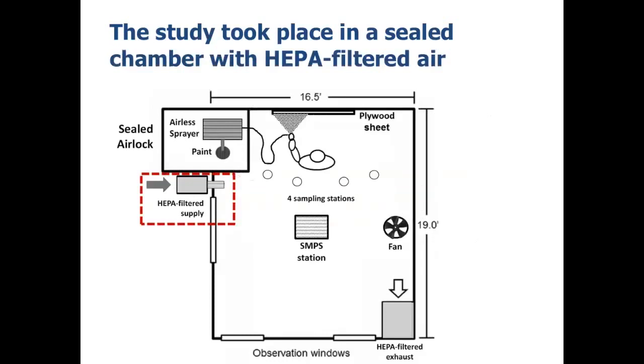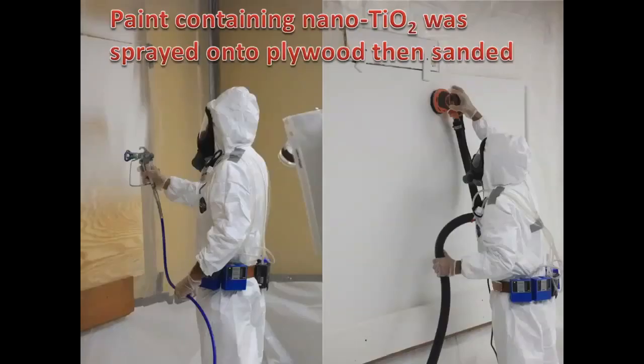The study took place in a sealed chamber with HEPA-filtered air. So the HEPA-filtered supply is highlighted by the box with red dashes on the left side of this diagram that shows the setup while spraying. Here are some actual photos of the chamber where the paint containing nano-TiO2 was sprayed on a plywood and then sanded by a tradesperson wearing full protective gear. The airless sprayer is shown on the left, and the power sander is hooked up to local exhaust ventilation on the right. Sanding was also performed without local exhaust ventilation and using unpainted boards for comparison.